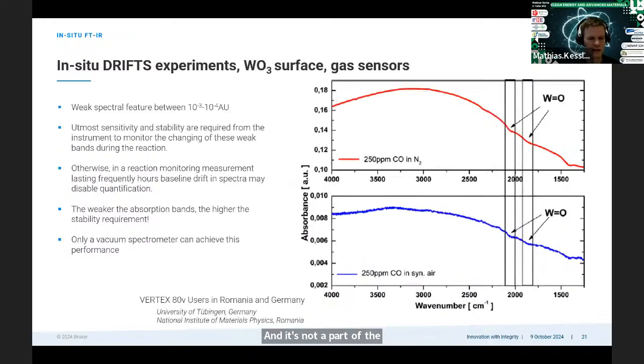And finally, we can also use tungsten oxide as a gas sensor, and we can track what is happening on a tungsten oxide surface with such a DRIFT reaction cell. Here we see the spectra, and you see only slight changes in the baseline, and here bands are going down, and these bands are significant for gases which are attached to the tungsten oxide surface.